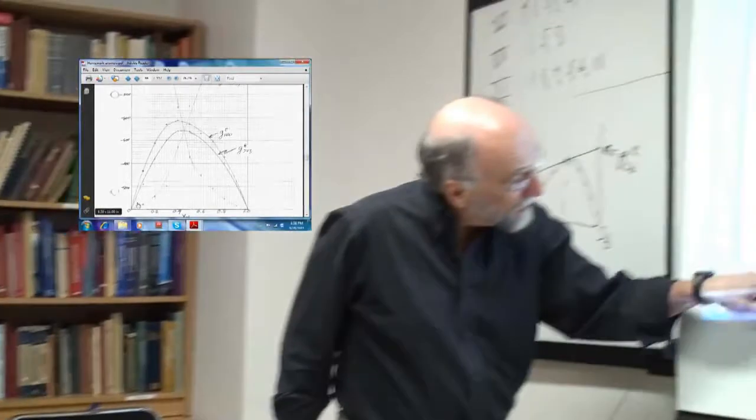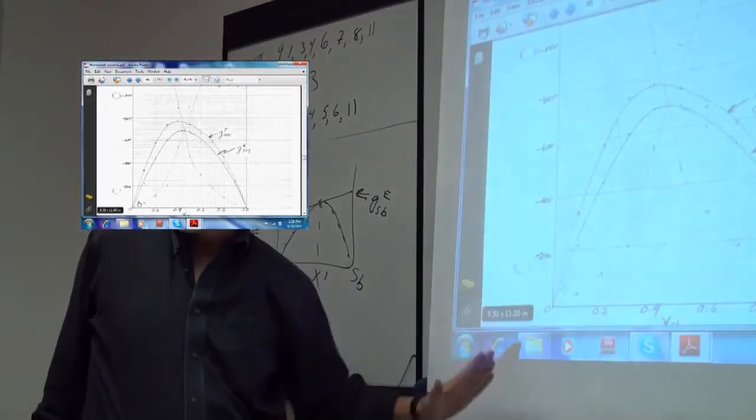And it's worth noting that these go up to limiting values. They do not go up to infinity or minus infinity. I didn't draw this on the graph, but this goes up and would meet the line at 2300. So that is the excess Gibbs energy of cadmium in pure zinc. It's not equal to infinity. That's related to the fact that the limiting tangent at 0 does not have an infinite slope, it's a finite slope.